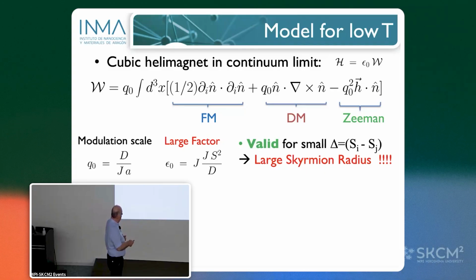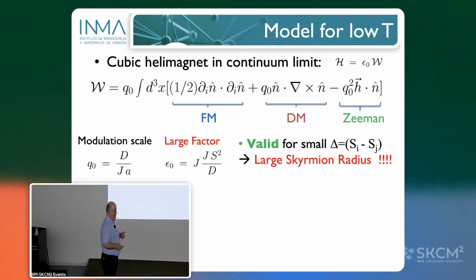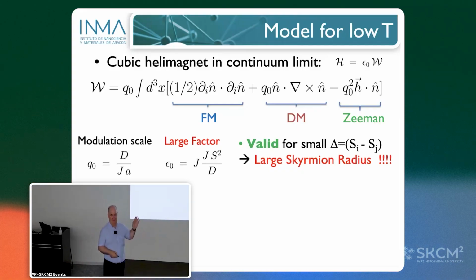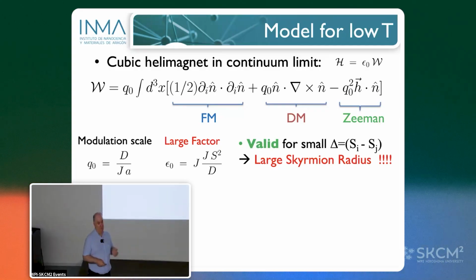We are allowed to do this if the change of the spin from site i to site j is small. If not, we cannot go to the continuum limit. If we are considering objects coming from frustration of interactions, in which the spin is changing strongly from one point to the other, maybe this cannot be applied. Even if everyone applies it, this is something to think about. Maybe we are doing a theory that cannot be applied to explain things in which we are considering frustration of interactions. However, if we are using the Dzyaloshinskii-Moriya interaction, usually the periodicity is very large. That means that from one spin to the other, the spin is changing smoothly, and the continuum limit is allowed, is possible.